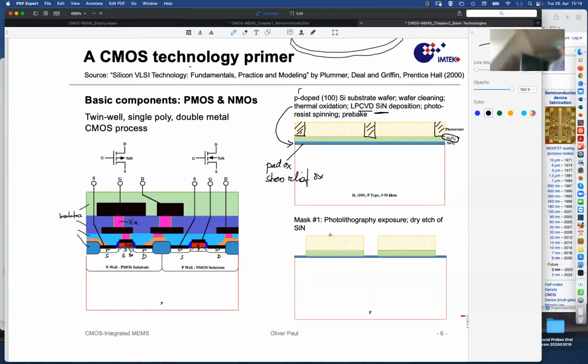nitride. That is going to be some rough process, either a dry etching process or maybe using phosphoric acid, but probably more a dry chemical process, some reactive ion etching process. And so that used a first transfer of a design, a first mask. Geometry has been transferred into the photoresist, and now, thanks to the photoresist protection against this reactive ion etching process, it has also been transferred into the silicon nitride.